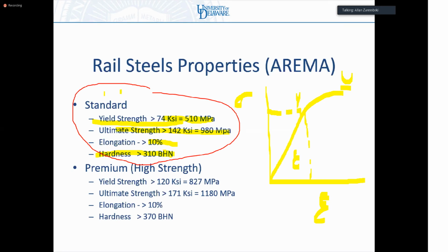So this is standard steel. By the way, to put things in reference, normal structural steel, the type you use to build buildings, is somewhere between 200 and 250 megapascals yield stress. So the yield strength of standard rail steel is better than double that. For example, in the US, we use what's called A36 steel. A36 steel is about 250 megapascals. So it's about half the strength of standard rail.